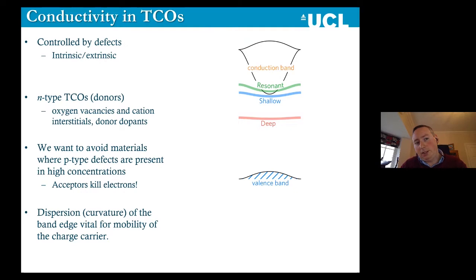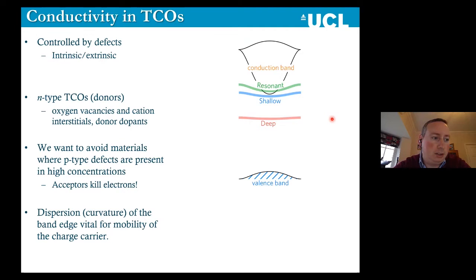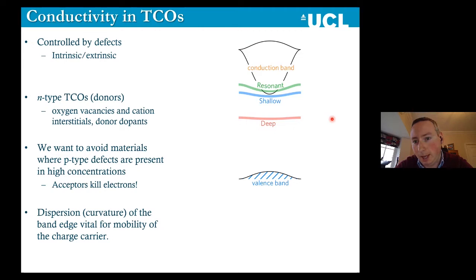Typically, when we look for these types of systems, we look at the behavior of different dopants and characterize each as either deep donors, shallow donors, or resonant donors. A deep defect is any defect that is further than kT from the band edge — so further than 0.025 electron volts. A shallow defect is anything within kT of a band edge, so at room temperature this defect will be able to excite its electron from the defect level into the conduction band. Ideally, you'd like a resonant defect — one where the defect injects directly into the conduction band, meaning that you already make a metal.